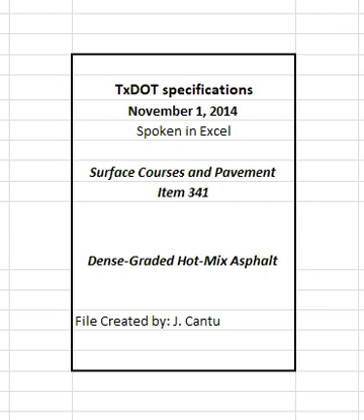Use the control strip method shown in Tex-207-F, Part 4, on the first day of production to establish the rolling pattern that will produce the desired in-place air voids unless otherwise directed. Use tamps to thoroughly compact the edges of the pavement along curbs, headers, and similar structures and in locations that will not allow thorough compaction with rollers. The engineer may require rolling with a trench roller on widened areas, in trenches, and in other limited areas.